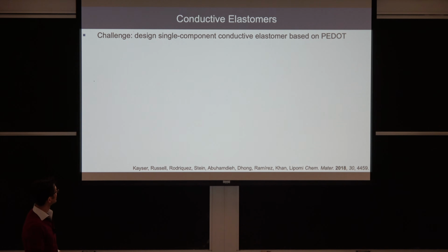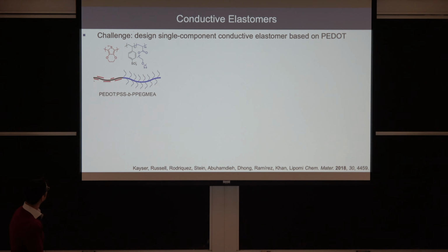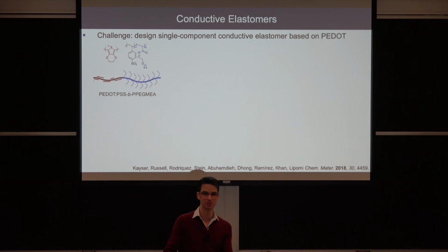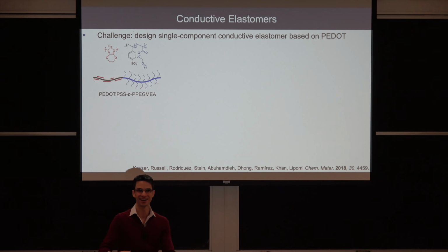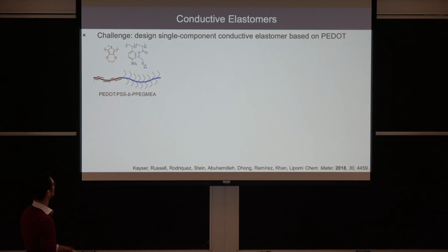And the last slide I want to show you is we're interested not just in the semiconducting part, but also the conducting materials, because those are what you make electrodes out of. So this is PEDOT:PSS. It's used as anti-static coatings. It's conductive. What we wanted to do is make this kind of bottle brush polymer, and then make the conductive part here. And the bottle brush polymer is really slippery and wiggly. It kind of looks like proteoglycans, which are like hyaluronic acid in the joints and stuff, to be really deformable.